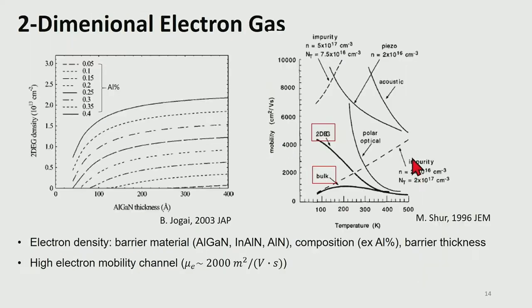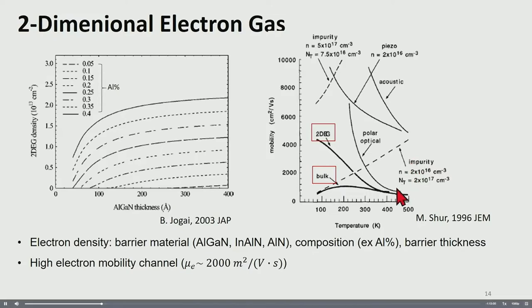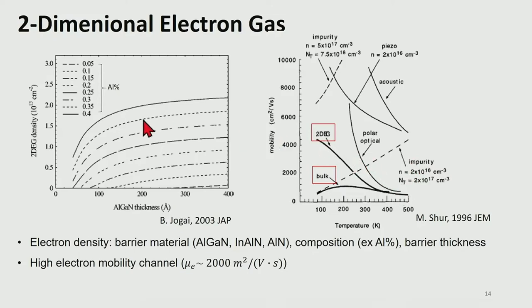Since the origin of the 2DEG channel is the polarization field in the AlGaN barrier, its electron density is also determined by the AlGaN barrier design. For example, by increasing the aluminum percent in the AlGaN barrier, or by thickening the AlGaN thickness, we can increase the 2DEG density. So typical 2DEG density level is about 1E13 per square centimeter, which is pretty high.